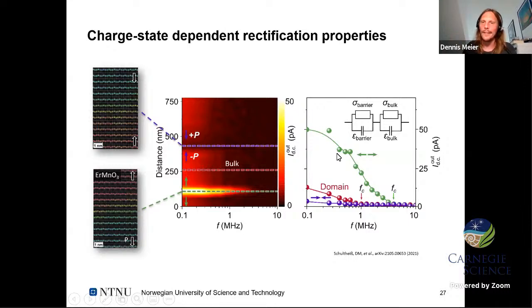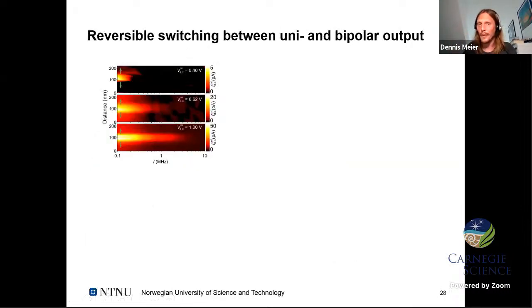Another important thing is now that this contact is also voltage dependent. So if you change the voltage, we also have contributions from the interface. The barrier is voltage dependent, so it's not just the conductivity of the wall determining the transition frequency, also the voltage dependence of the interface. And you can see that here, at 0.4 volts, for example, I see no signal in the AC.